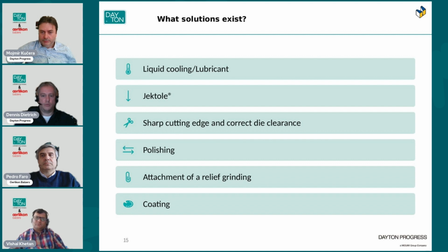Edge radius punch points for the softer aluminium grades should be avoided. A flat sharp edge punch point without any shear angle and the correct die clearance performs best. The shear has a tendency to only deform the aluminium and cause more rollover in the hole in the softer aluminium grades.